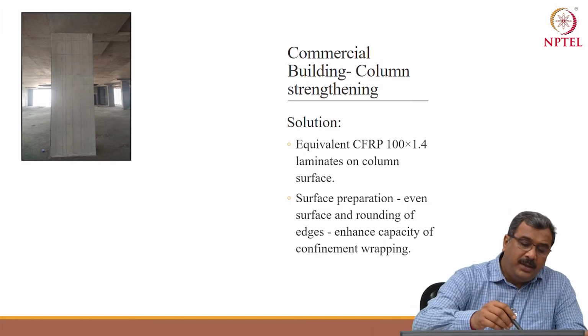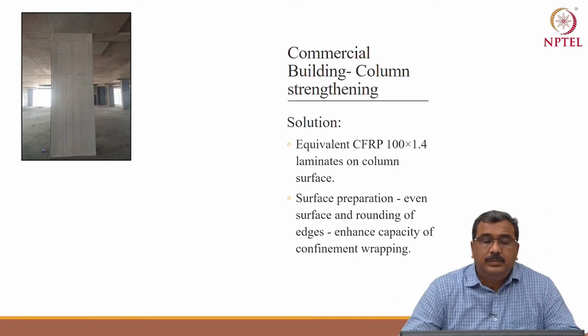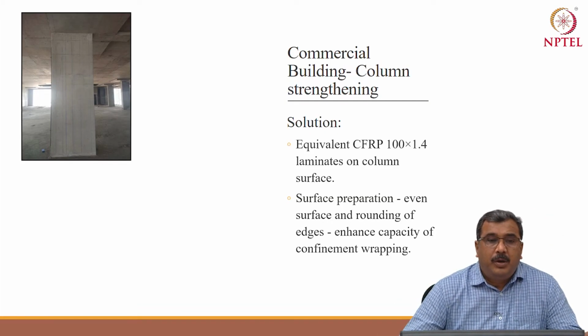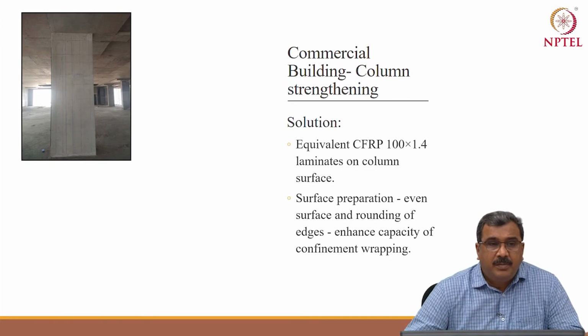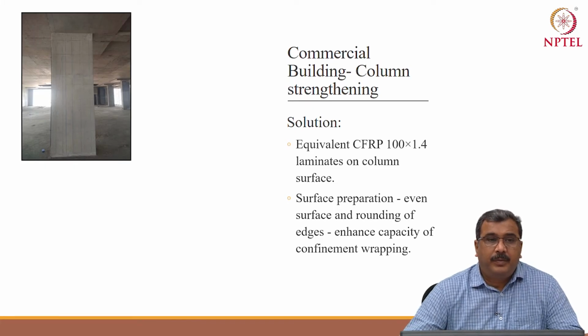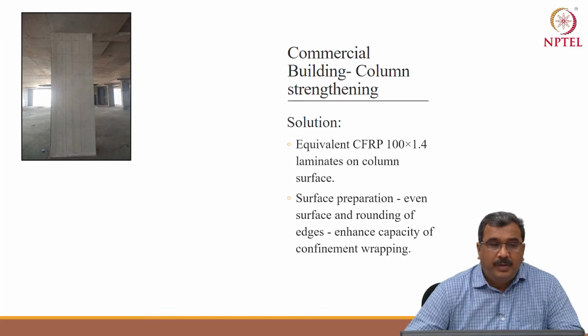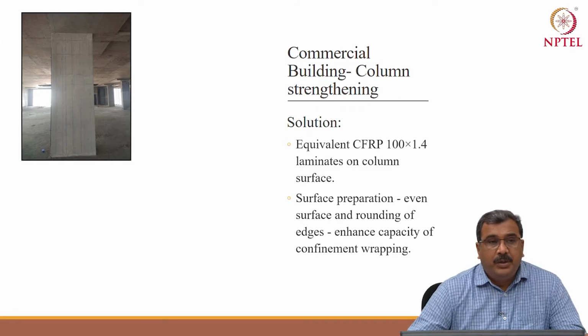Also, the edges were rounded because there is a partial confinement also, for enhanced moment to take care of shear and compression, and to avoid delamination of the laminates. So rounding is very important.